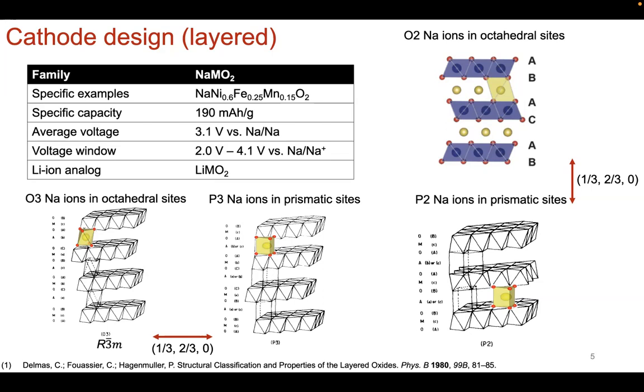So what you see here are the different types of structures that the NaMO2 family of compounds can take. You can see the crystal structure, what's called the O3 type, and that's where sodium ions sit in the octahedral sites, as outlined in the little yellow octahedron schematic here. Now, as sodium ions are going in and out, they could also sit in the prismatic site, or the P3 type structure. In terms of synthesis, you can also synthesize layered compounds where the sodium ions can sit in this octahedral site but then also occupy a different prismatic site. And depending on the synthetic conditions, you can have your compound go in between the O2 and P2 sites.